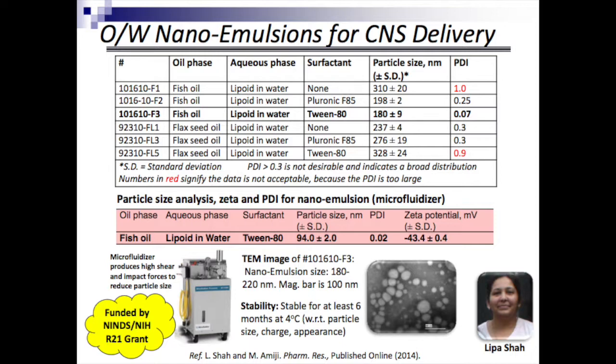And we test all of our emulsions both at 4 degrees Celsius as well as at room temperature. And we ensure that even for lab scale preparation methods, we have stability for up to 6 months. We measure that using a light scattering approach to make sure that the oil and the emulsion remain stable. There is no phase separation between the oil and water phases. And we also want to make sure that the drug that's encapsulated remains stable.